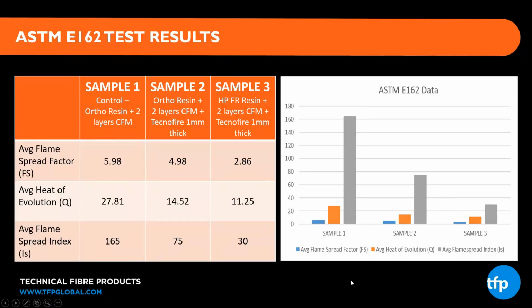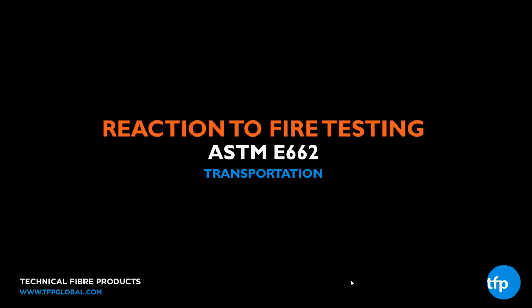Next slide, please, Neil. So one thing I did want to point out before I forget, because these panels were also used in a 662 test, the resin we use, the high performance flame retardant resin, generally would want about a 200 parts per 100 loading of ATH into the resin, the filler. We were able to scale that down to 65 parts. So you can think about the viscosities and the throughput in an end part, what effect that would have. So we also ran a 662. Now 162 and 662 make up what's called document 90, which is a test requirement in the transportation field. A lot of times you'll see that in the States in rail and bus designs. So these 2 combined make up the Doc 90. So next slide, please, Neil.